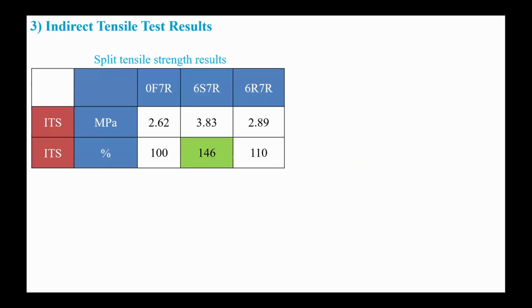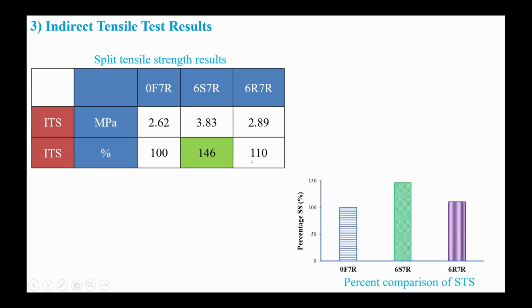By comparing the results of indirect tensile strength, we compared the split tensile strength. The industrial steel fibers improved the indirect tensile strength by 46%, while there was no significant improvement by the recycled steel fibers. That was 10%, but much better than that of the plain concrete.